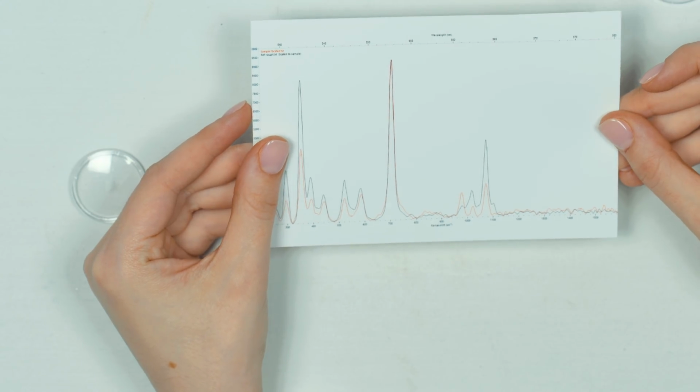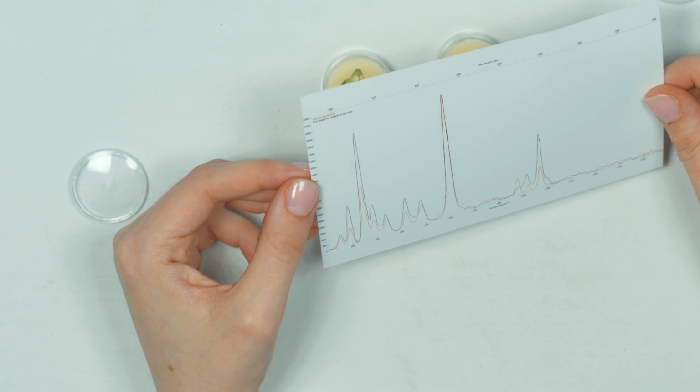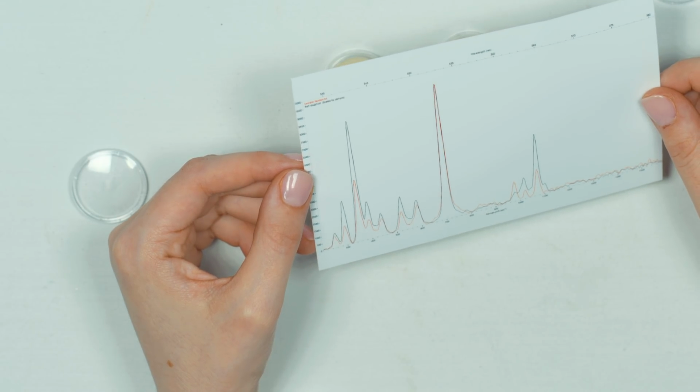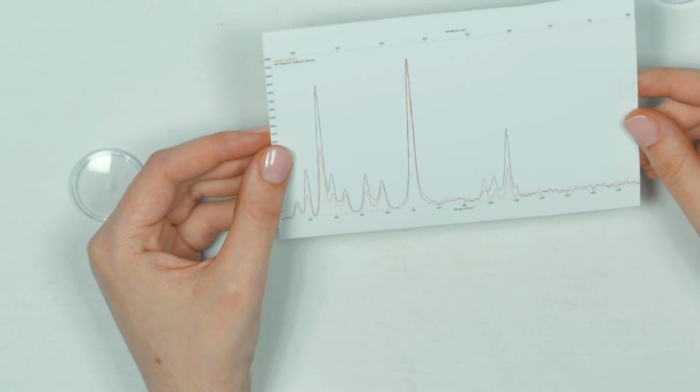So yes, we know when light interacts with a material, in this case gemstones, some of it is absorbed, and that's what leads our brain to process the color. Right. So for this material, all the colors of the rainbow would be absorbed except for the green, and that's why our brain tells us it's green. But with Raman, the nice thing about this same interaction is that some of the light is actually scattered as it leaves the material, at a slightly different wavelength than we would expect. And it gives us almost a DNA fingerprint of all the different mineral and gem materials.